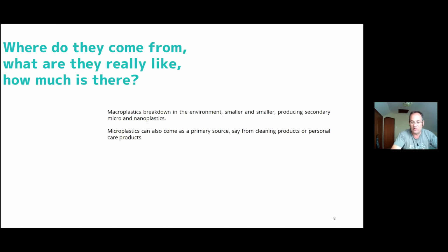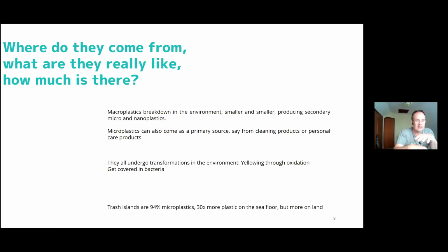We know that oxidation driven by ultraviolet light can lead to yellow discoloration, and they can get covered with bacteria, as I mentioned before. We've seen these large oceanic trash islands in documentaries. Well, actually, 94% of those are made of microplastics that you cannot see. So all the things you see in there are the 6% that you can actually see. However, for as much as there is in there, there's actually 30 times more plastic on the sea floor.